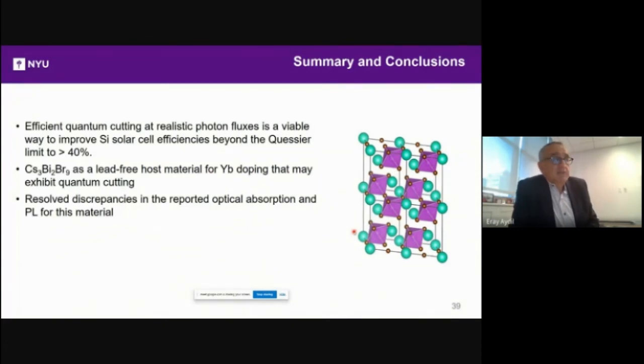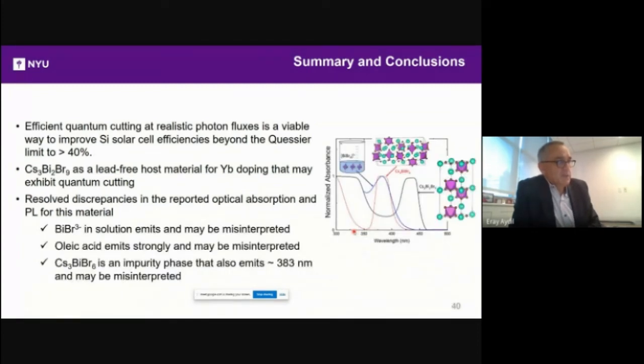These bismuth-based perovskite materials are interesting as lead-free host materials for ytterbium doping, and they may exhibit quantum cutting. We resolved some discrepancies in the reported optical absorption and photoluminescence for this material. One has to be careful because there are lots of things in the liquid that emit and absorb, and we like PVD where such contamination is absent. So one thing is that the bismuth bromide octahedra in solution emit and may be misinterpreted. That should be BiBr6 3- in solution. Oleic acid, which I didn't show you, emits strongly and may be misinterpreted. And moreover, there are impurity phases, like the Cs3BiBr6, which emits a lot like the BiBr6 octahedra. It also emits at 383 and may be misinterpreted. So one has to do really careful work.